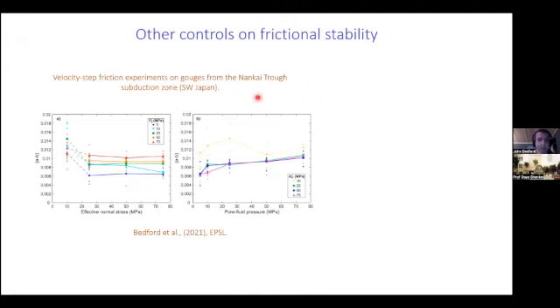But what we did here is we tested fault gouges collected from the Nankai Trough in Japan via IODP drilling. So we took the same material and tested it over a range of different pore fluid pressure and effective normal stress conditions to see how that affects the A minus B and the stability of the gouge. And we found that once we get to effective normal stresses of above 25 MPa, that A minus B is pretty much exclusively controlled by pore fluid pressure.